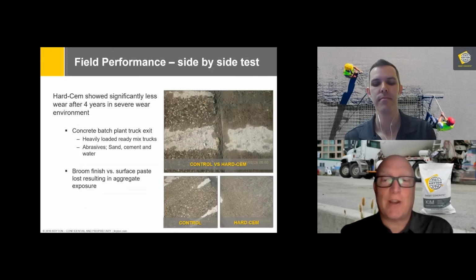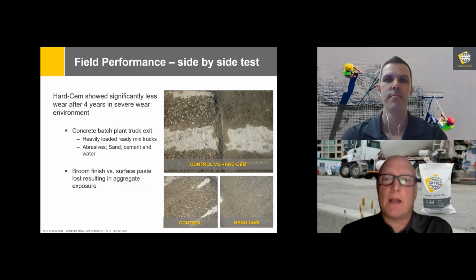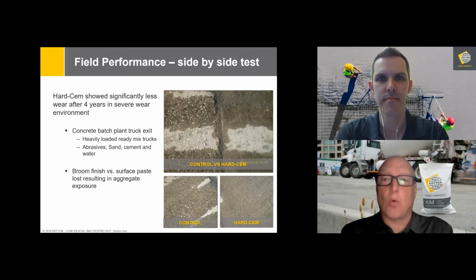Jeff, this is a great example of the performance we can see in real world environment with Hard-Cem. This has been placed at a concrete batch plant where the heavy machinery, the loaders, and the trucks are constantly driving over the concrete. The concrete company placed the Hard-Cem concrete directly next to control concrete. And after 4 years, you can see that the control concrete has worn down the paste right down to the aggregate. And then in the Hard-Cem sample, we can still see the brooming of the concrete while they're finishing it. It's a great example of the performance that you can expect to see in a very harsh environment.